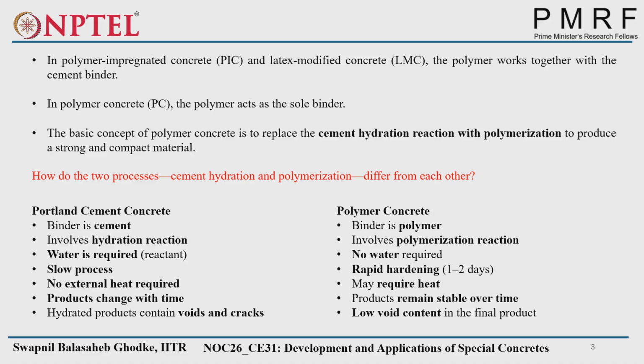But in the case of polymer concrete, the binder is a polymer and it involves the polymerization reaction. Here, no water is required, and hardening is rapid, 1 to 2 days only. In the case of Portland cement concrete, the days required for hydration are more than for polymer concrete. Full hydration we consider as up to 28 days. In polymer concrete, due to the absence of water, we require heat from an external source. Then products remain stable over time, with low void content in the final product. So these are the differences between Portland cement concrete and polymer concrete.